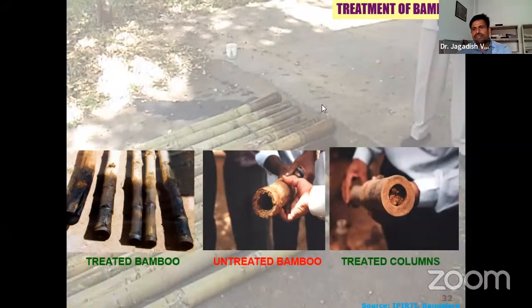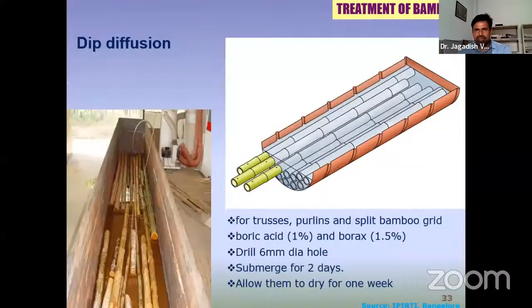Once you treat it, to check whether the bamboo got treated or not, you can test it using the graveyard test, wherein, as I told you, you take a 2 feet bamboo and bury half of it under the insect mound. Then you check the treated and untreated portions every now and then, like after a month, 3 months, 6 months, and 1 year, to see how the bamboo is performing. Typically the treated bamboo will be fine, and the untreated bamboo, slowly the insects will eat it. You can see the perished bamboo.